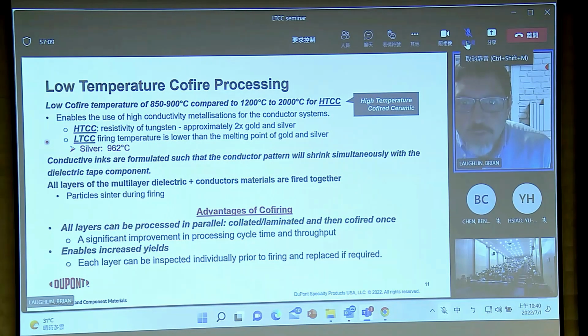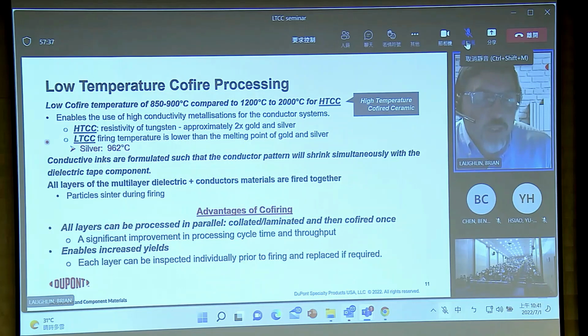But we call it low to differentiate from its high temperature co-fired ceramic variant, where you're actually sintering ceramic particles without glass. And that's usually something more like 1200 degrees to 2000 degrees C. The reason this is an important distinction is not just because of the energy input for lower temperature firing, but in HTCC, you are above the melting point of high conductivity metal traces. And so usually you're restricted to something like tungsten or molybdenum as your conductor material, which has particularly poor conductivity compared to things like gold or silver or copper.